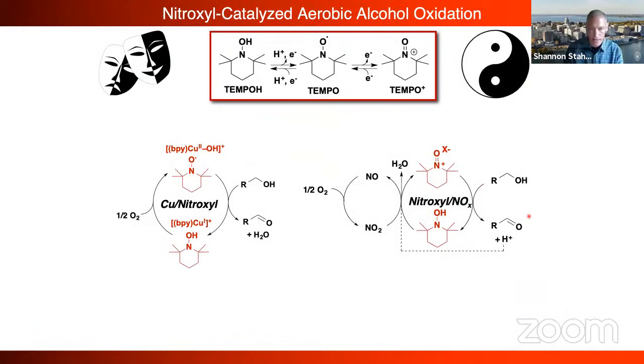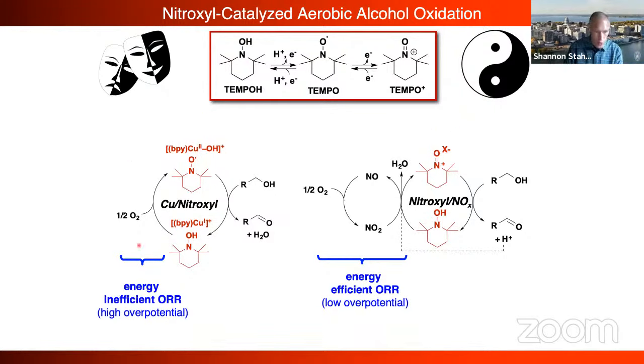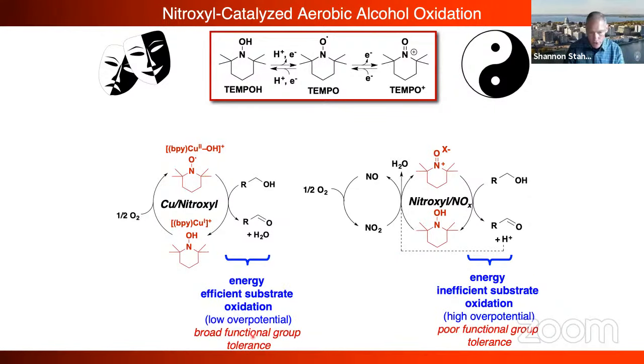What does that mean? Let's just kind of look at that. What we basically have done is by combining copper and TEMPO, we've converted the nitroxyl copper system into a weak oxidant compared to a strong oxidant. What did that do for us? That conferred remarkable chemoselectivity. So now we can tolerate all those oxidatively sensitive groups. So in this case, you could argue that what we wanted to do was actually waste ORR potential, right? We don't want O2 to be a strong oxidant. We want to knock it down and turn it into a very mild oxidant, because now we get the broad functional group tolerance because we've got a very mild oxidant with low kinetic barriers.